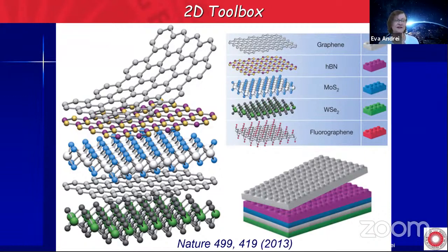Now you may ask, okay, why can't we just grow these with molecular beam epitaxy? Why can't we grow this in the lab? It turns out that most of these materials will not grow spontaneously. When you grow crystals or when you make layers in your MBE machine, what grows there is what nature dictates is the most stable compound. And many of these layers that you can actually superpose, you can actually not achieve in any other way.